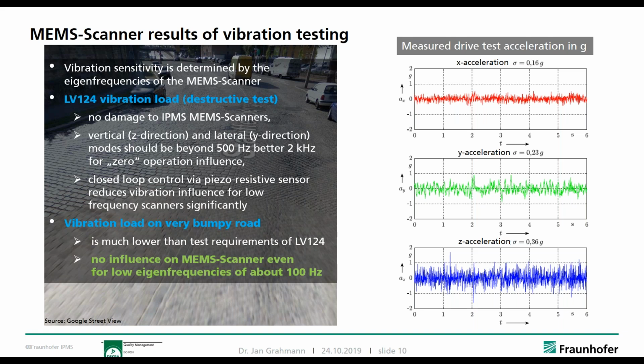So the other point is, when you are in the range of below 500 Hertz, we saw that via closed loop control for these quasi-static axes, we can improve the vibration resistance of the scanner significantly. But all these points here are valid for the LV124.